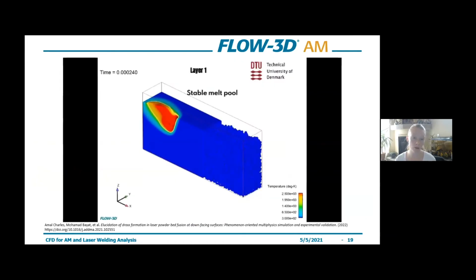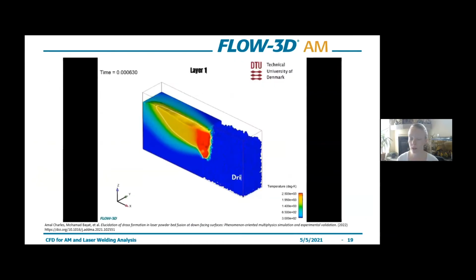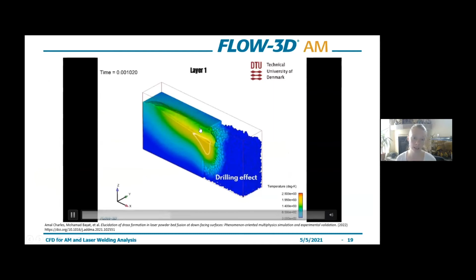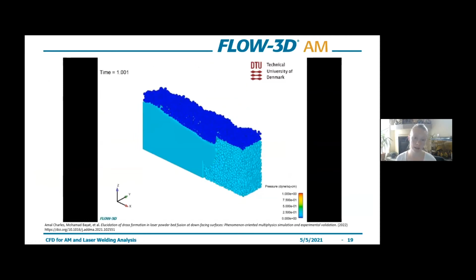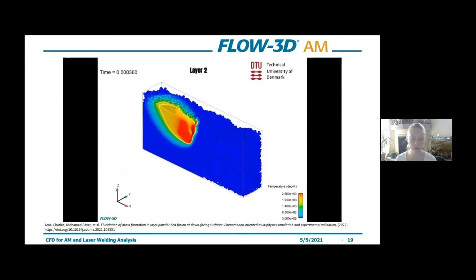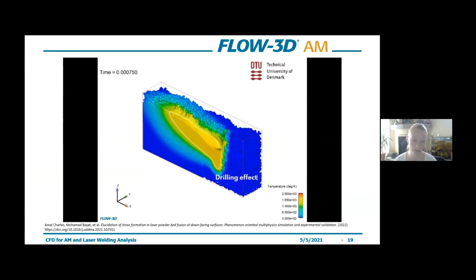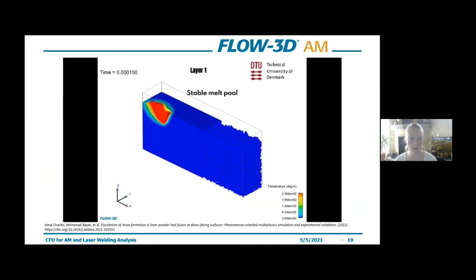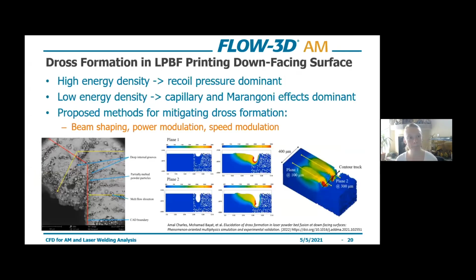And this leads to what they call dross formation, where you get this sort of drilling effect as you go over the edge from the dense to the powder material. And that can lead to undesirable fusion conditions and other defects that we're trying to avoid when going from one media to the next. So qualifying this, understanding what are the forces at play that are leading to this, what can we do to mitigate dross formation and create a more consistent print when you're going on to different medias.